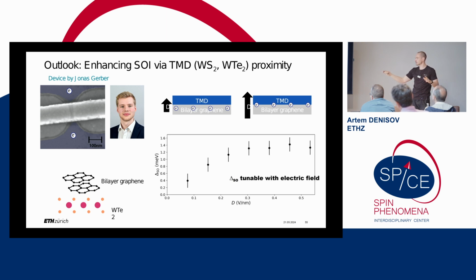Okay. On the side, there is another direction in bilayer graphene activity in our lab, which I think is very interesting, and very soon we will see results from it. It's enhancing spin-orbit coupling using TMDs like tungsten disulfide and tungsten ditelluride. The idea is that if you put a sheet of TMD next to bilayer graphene, since tungsten is really heavy, our hope is that we can induce bigger spin-orbit coupling in the bilayer graphene than the intrinsic one, in order to drive your spin qubit with classical EDSR.